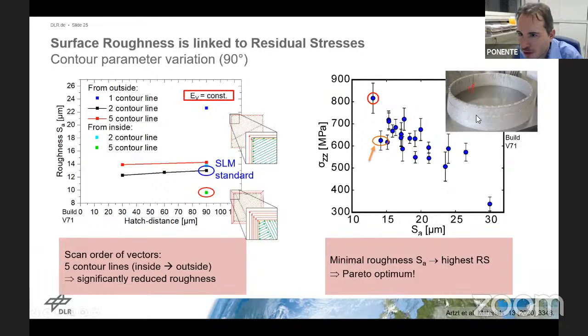On the top, we see a little image of an injector ring, and you see here cracks in the surface. This one was manufactured with the parameters that gave us the best surface quality, so on the left-hand side with the red circle here. But the residual stresses here are so high that the injector ring cracked where the inside channels are positioned. So it's actually a poor manufacturing strategy. So we had to go for kind of an optimum or a compromise here, allowing for a little bit of improvement in terms of surface roughness and not too high residual stresses.